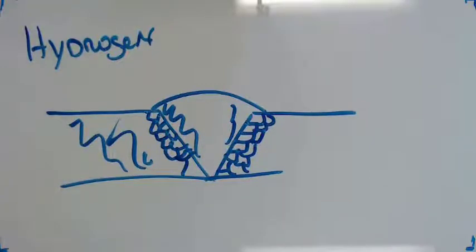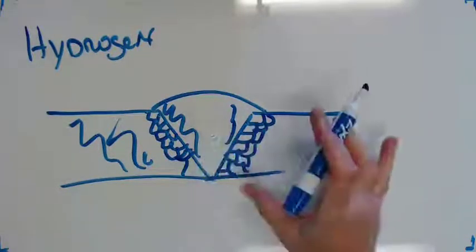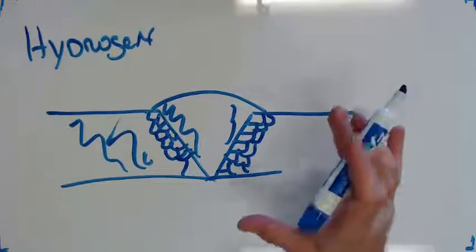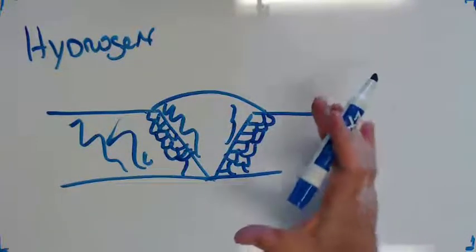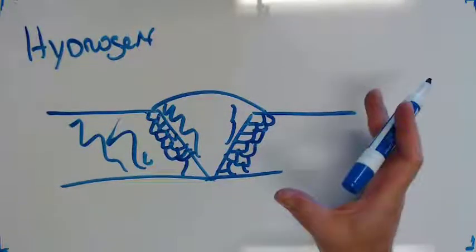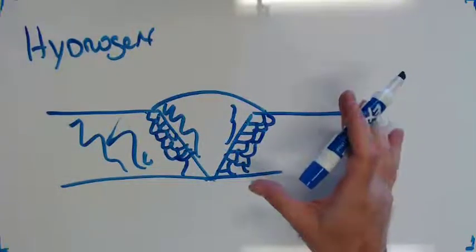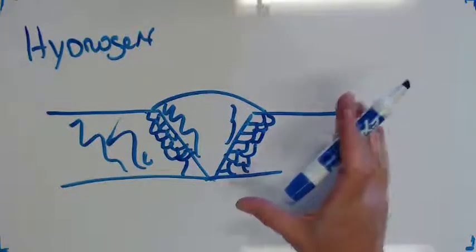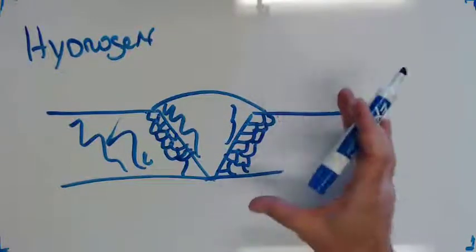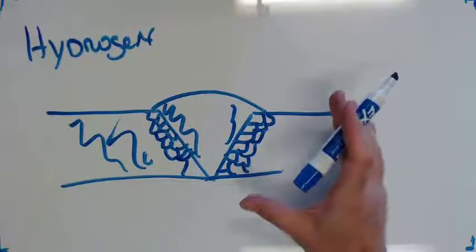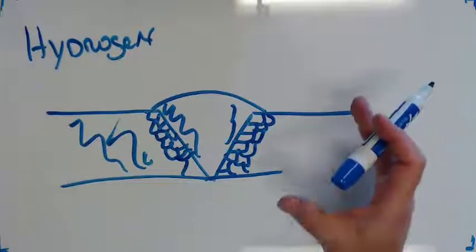When you preheat something with a torch, what do you see when you put the torch on it? You see moisture flash off of it, just condensation out of the air. If we don't do preheat, that will put hydrogen into our weld. What else could be a source of hydrogen? Hydrocarbons, oil. That's why it's so key to get all the oil off of parts before you weld them. Moisture not just on the steel, but wet 7018. If 7018 has been left out in the open, it's no longer low hydrogen. It's absorbed moisture out of the air and that water is H2O. There's a lot of hydrogen in a water molecule.